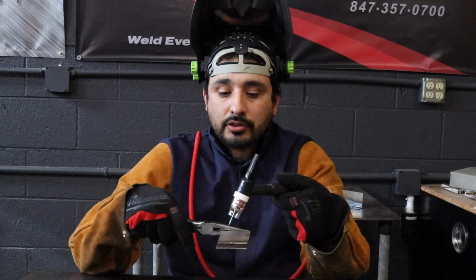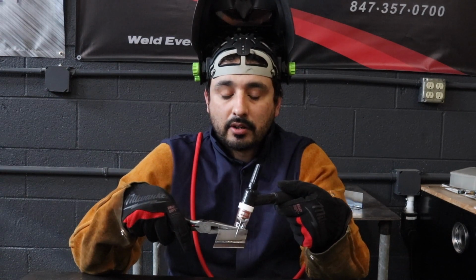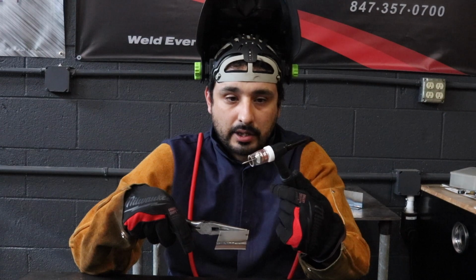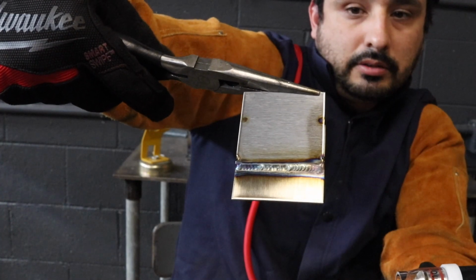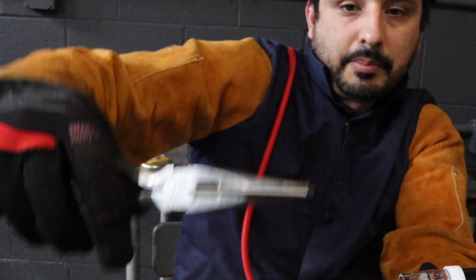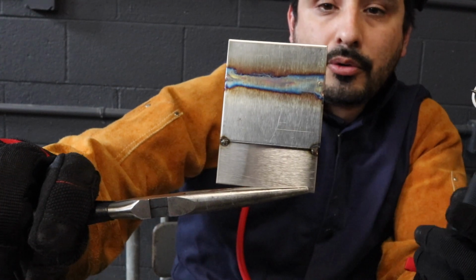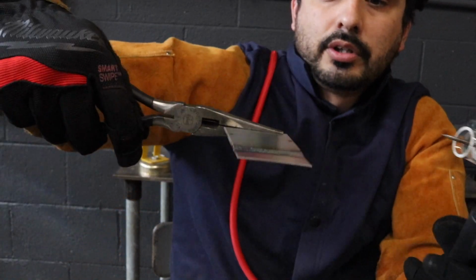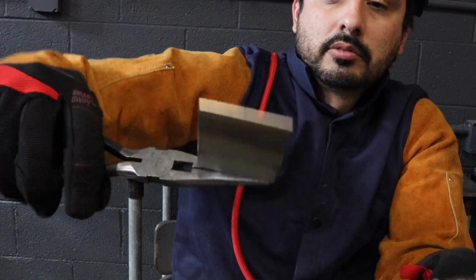So next up, we did weld some stainless steel 304 16 gauge. As you can see, we had excellent gas coverage with our Edge cup. This is the weld, and if we want to go to the back side, you can see that there is no burn through, and we have pretty good heat affected zone both sides.